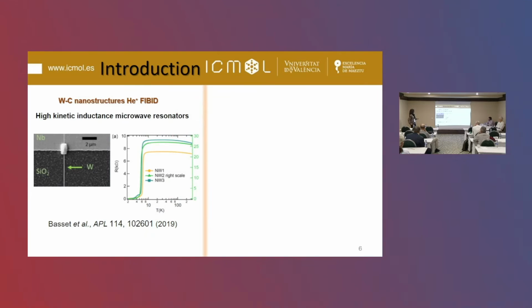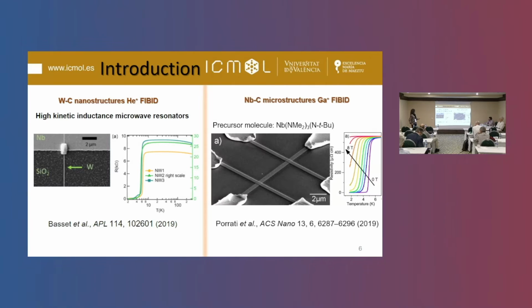More recently, other authors have been reporting tungsten carbon nanostructures grown using the helium beam, and later on using a different precursor material. It's also possible to grow niobium carbon microstructures using the gallium focused ion beam. The superconducting properties of those materials are comparable to those of the tungsten carbon wires reported previously.